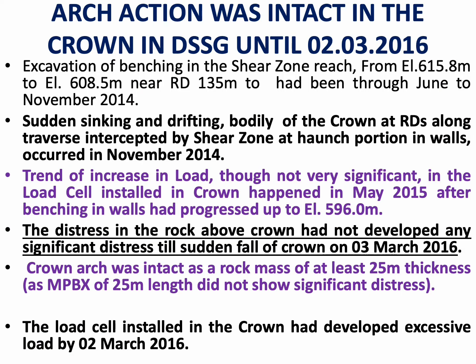Arch action was intact in the crown in the downstream until 2nd of March of 2016. Excavation of benching in the shear zone reach from elevation 615 to 608 near RD 135 had been through June to November 2014. Sudden sinking and drifting bodily of the crown at RDs along traverse intercepted by shear zone at haunch portion in the walls was noticed to have occurred in November 2014. Trend of increase in load, though not very significant in the load cells installed in the crown, happened in May 2015 after benching in the walls had progressed up to elevation 596.